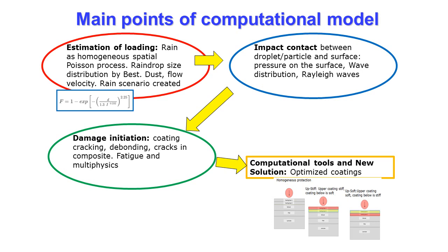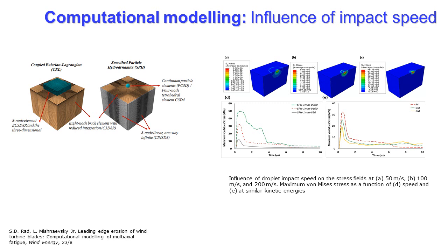Coating optimization. We at DTU carried out a number of computational studies of the erosion of wind turbine blades. A computational model of a rain droplet hitting the blade surface was developed, based on the smooth particle hydrodynamics method. The effect of the droplet impact speed was investigated. It was observed that peak stress in the coating increases with increasing impact speed. An increase in the droplet velocity from 50 to 100 meters per second leads to 3 times higher peak stress.